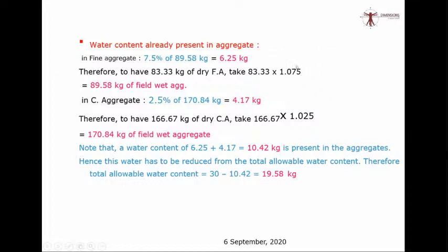So based on the percentage of moisture, either assumed or derived from scientific methods like an infrared moisture meter, etc. If for example you have got 4.5 percent moisture, if you are using a moisture meter and checking it, you will have to multiply 83.33 by 1.045. I got 0.045 by dividing 4.5 by 100. So you will get 89.5 kg of fine aggregate when you have assumed 7.5 percent of moisture.